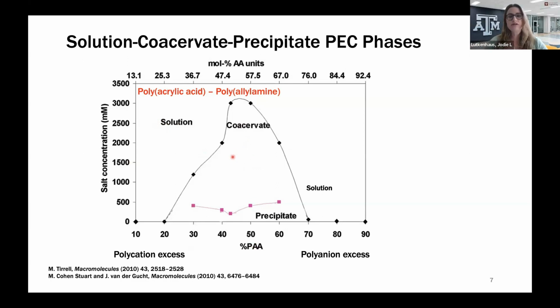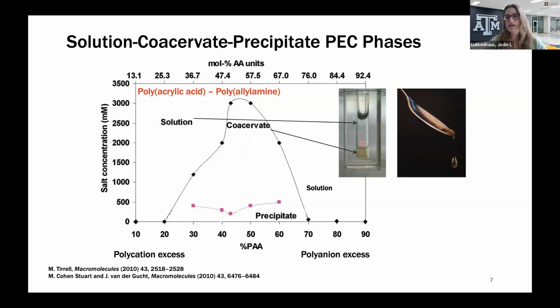In this region, where you're closer to about 50-50 by repeat unit, or equimolar charge compensation, and you have a higher salt concentration, you can have what looks like a liquid-like coacervate. So this is a liquid-liquid phase separation, where the supernatant represents the solution, and then the bottom is the liquid coacervate, and it tends to have a thick gel-like or honey-like consistency. And of course, if you add enough salt, you move upwards in the phase diagram. If you add enough salt, you can screen the interactions completely and come back to the solution.